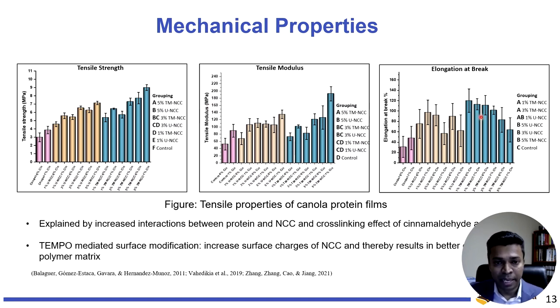Elongation at break shows how stretchable the material is. Usually when we increase the strength of the material, the stretchability of the material will reduce, which is why you would see with the increased tensile strength that there is a reduction in the stretchability of the material, but still with the nanocellulose, the elongation at break or the stretchability of the material is still better than the control films.